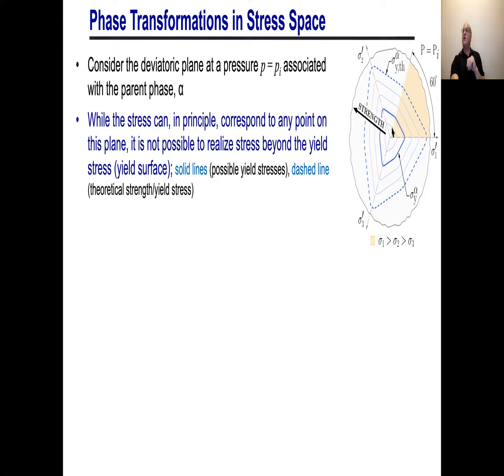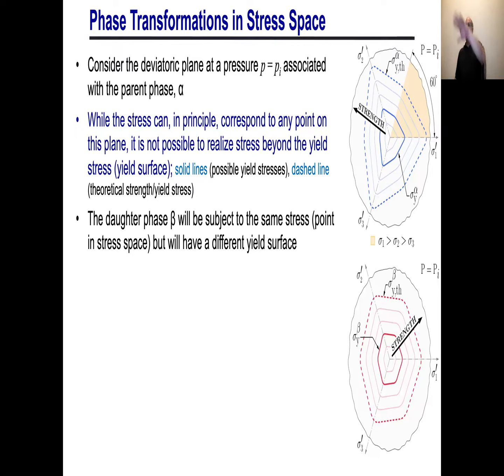So the yield strengths, or how far we can go out, go anywhere from 0, if the material has a 0 yield stress, all the way out to whatever the theoretical strength is, which is roughly the shear modulus over 2 pi, which actually turns out to be a pretty good estimate. Okay, so that's one material, my alpha phase. If we're talking about iron, that's the BCC phase. And the daughter phase is a different crystal structure, and it has its own set of yield surfaces, which represent its own symmetry. And so these are the yield stresses for the phase beta, for the daughter phase.